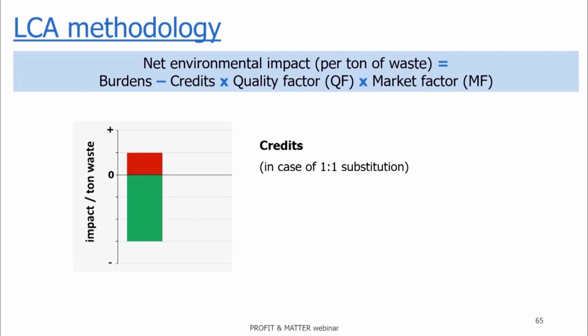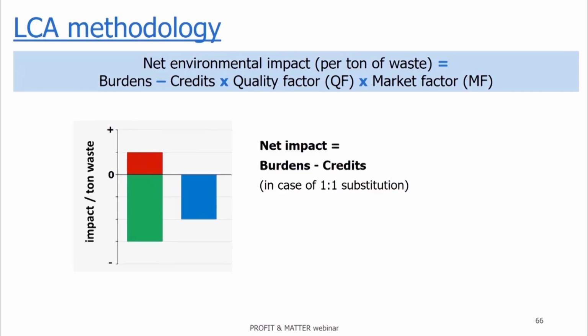In case of 1-to-1 substitution, we assume that 1 kilogram of recycled material substitutes 1 kilogram of virgin material. Third, the net impact is calculated by subtracting the credits from the burdens. The more negative the value, the better. However, to account for the potential different technical quality between the mechanically recycled materials and their virgin alternatives, the credits are multiplied with a quality factor based on mechanical properties. The quality factor is a value between 0 and 1.